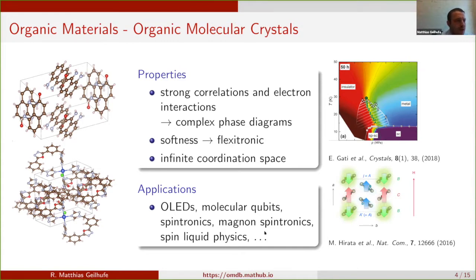But there are also other things mentioned, like people discuss organics in connection to qubits and to spintronic applications. Like I mentioned before, from the academic point of view, the spin liquid physics also plays a dominant role. If you take a look at this picture on the right with the emergent magnetism, as these molecules contain no magnetic atoms by themselves, they typically spin polarize with a magnetization of about 1 mu Bohr. And if you have a frustrated lattice, for instance, that one is almost on the verge of that, with this kind of triangular coupling between the molecules, then you start to set up frustrated quantum magnetism in these materials.